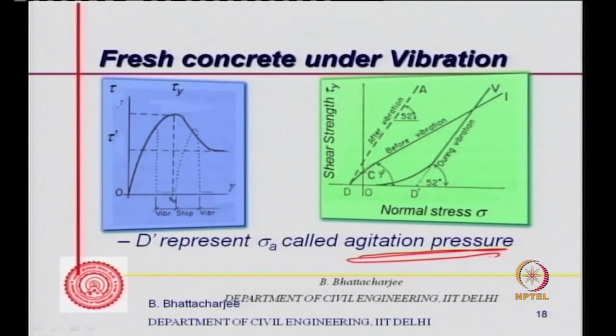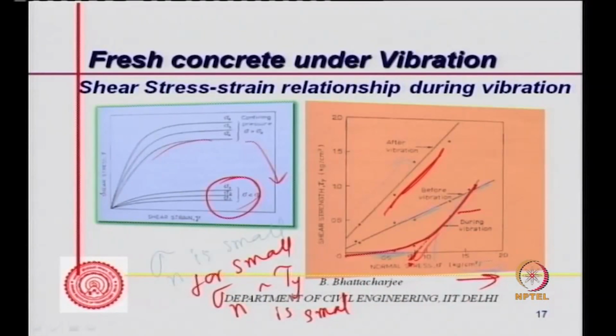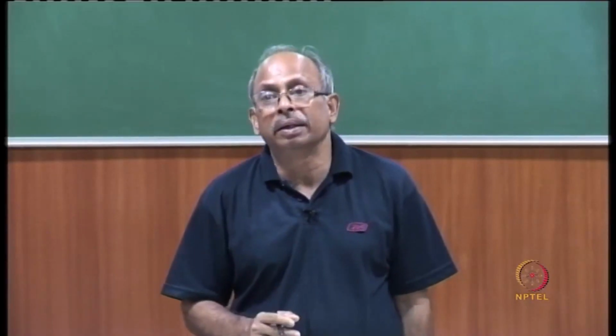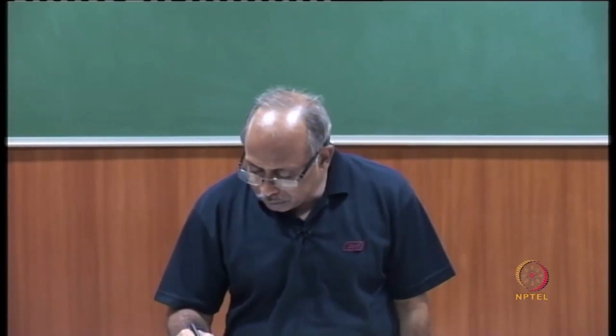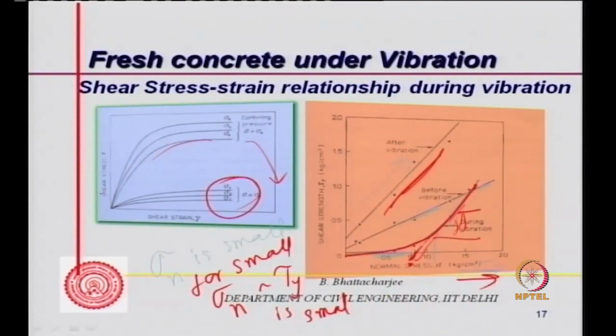So if the normal stress is less than the agitation pressure, which is actually the intercept, if I extend this line, this is during vibration. So this is the normal stress that will correspond to the agitation pressure. So during vibration, it is like this, and you can go back to the earlier diagram again. This is the agitation pressure here. So if your normal stress is more than the agitation pressure, only then does the yield stress start increasing. So the result of vibration is that the yield stress reduces significantly, but mu, of course, the slope of this one, is more than the original.